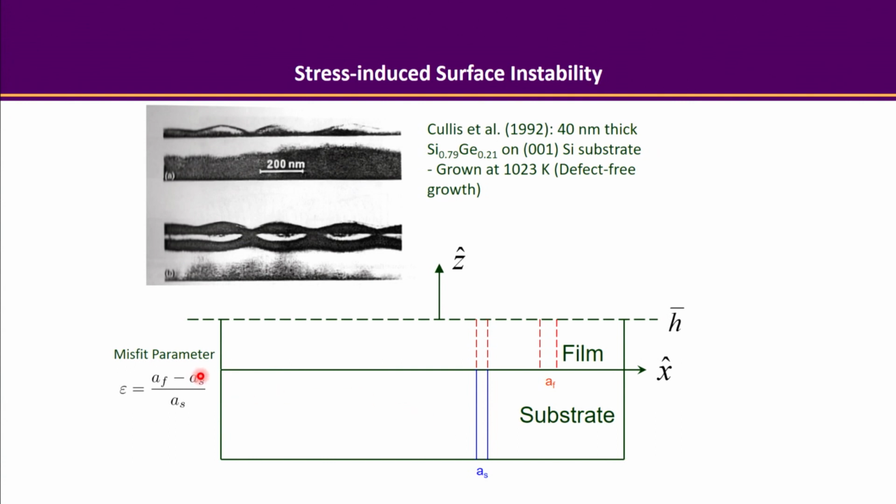So that they can have a very nice coherent surface here. As the film grows, you can expect that there will be strain energy being stored in this film, because if there's no strain, the film would prefer a larger lattice spacing, but due to that constraint, everywhere in the film is going to have strain energy here.